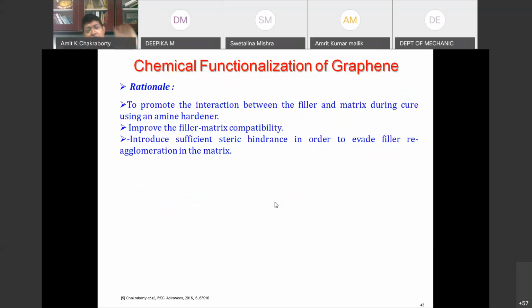So that is the reason why we chose, in 2010, when we started the same activity with graphene, we decided that instead of plain graphene, we shall first modify the graphene with some chemical bond that will interact very efficiently with the resin, because most of the resins are cured with an amine based hardener. So we thought if the graphene can be modified chemically by an amine group, then the graphene as a filler itself will start acting like a hardener.